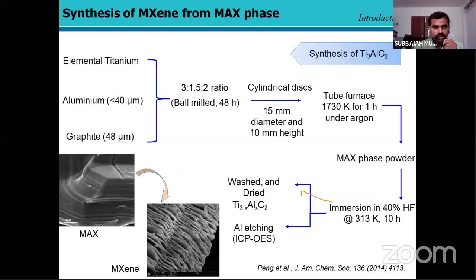How was the MXene material synthesized from the MAX phase? Initially they started with many methods, but this method is mostly adopted for the synthesis of titanium-based MAX phase. They started with a 3:1.5:2 ratio of elemental titanium, aluminum, and graphite-based material, which was ball milled for 48 hours. Then the powder form of this ball milled material was applied to a pressure instrument to make a cylindrical disc with a size of 15 millimeter diameter and 10 millimeter height. Then this disc was further treated in a tube furnace at about 1730 Kelvin for 1 hour under argon atmosphere. So the obtained MAX powder was titanium aluminum carbide, and this is the raw material for MXene.